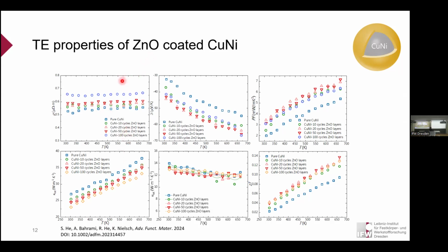For zinc oxide, what we can see is that with coating, we decrease the conductivity and increase the resistivity, which is also accompanied by a very obvious enhancement of the Seebeck coefficient, and which combined gives us a performance gain in terms of power factor. Also, thermal conductivity is decreased because of the enhanced electrical resistivity. So the charge carriers are scattered more, so the accompanying heat is also reduced. At the end of the day, we could see there is a performance gain in terms of ZT if we use this technology. Okay, so everything works fine for the metallic materials, but how about semiconductors?